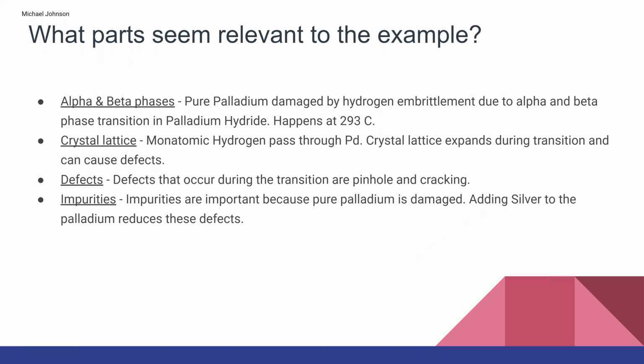What parts seem relevant to the example continued? Phase transitions are very important, which we talked about previously. Pure palladium is damaged by hydrogen embrittlement due to the alpha and beta phase transition in palladium hydride, which happens at 293 degrees Celsius. The crystal lattice structure only allows monatomic hydrogen to pass through the palladium sheet, and the crystal lattice expands during this transition, which can cause defects.